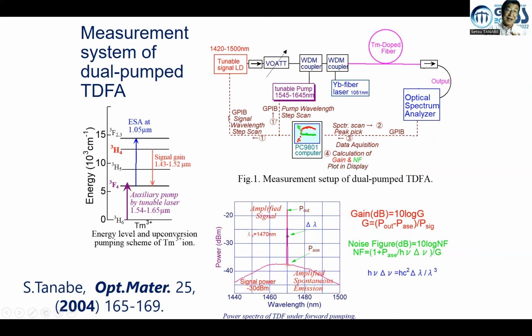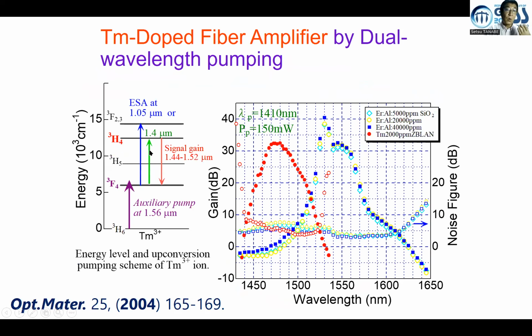And this is an introduction of TDFA, which is the S-band, 1.4 micron region, up to the 1.52 micron region. I was doing these amplification experiments already 20 years ago by utilizing a tunable signal laser diode and thulium-doped fluoride fibers, and measuring the gain spectrum. A dual-wavelength pumping scheme was very efficient, which is a kind of up-conversion, because population inversion between the third excited state and the first excited state was very difficult. This excited state absorption pumping was necessary to achieve population inversion, which is necessary for signal amplification.